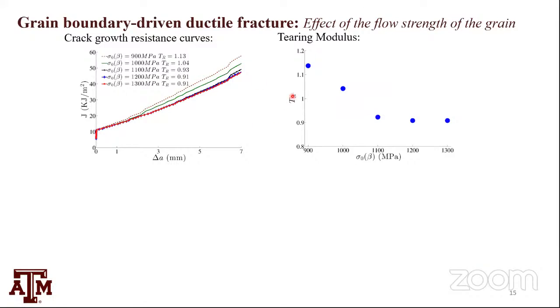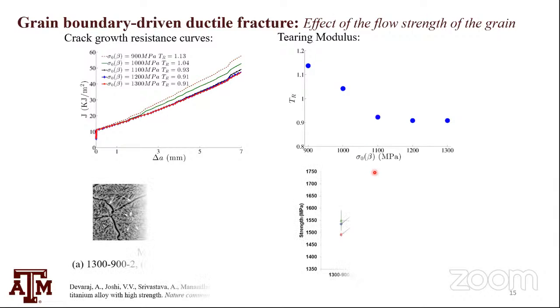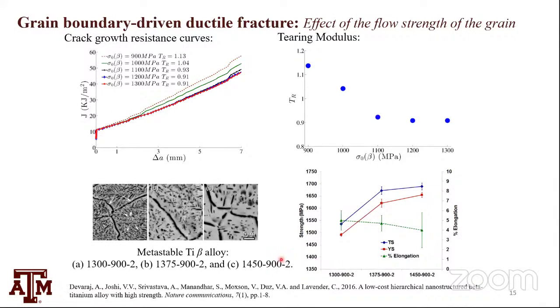We can get the tearing modulus, which is nothing but a normalized slope of these curves, and plot it with respect to the strength of the grain, because strength of the grain is what we can make. We can change the precipitated structure in a grain, and we can actually make grains with different strength in experiments. And by increasing the strength of the grain, we can increase the overall strength of the material by designing the precipitate. But when we increase the strength of the material, we lose toughness.